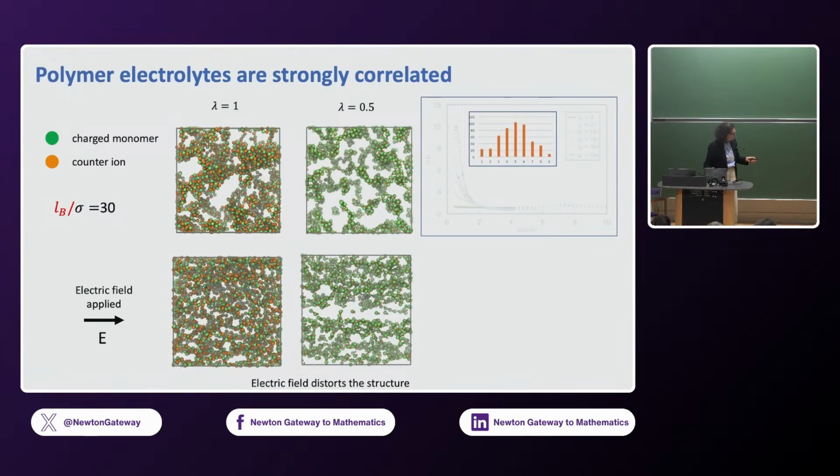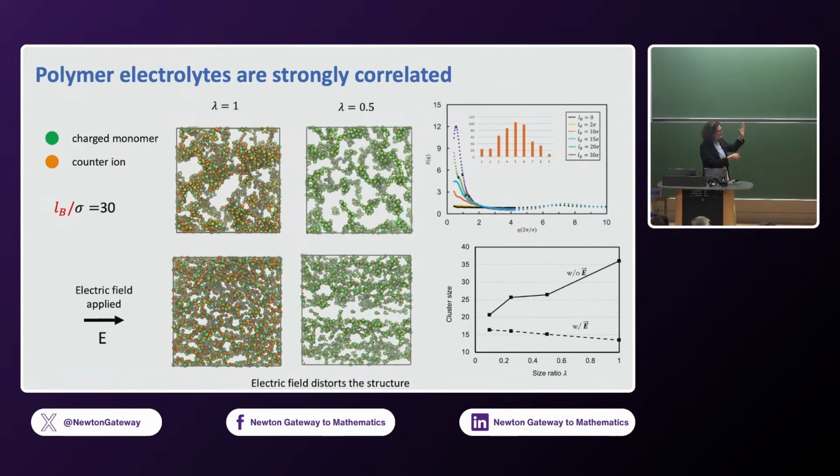And because we talk about multi-component systems, I like to also show this example. In these systems, the charges are random when you make them, so they are really multi-component systems. If you just take two components, if the molecular weight is, say, 50 or 20, you have 10 to the 20 different chains. So even if the mean concentration has some number like 0.5, they have completely different sequences. They are very multi-component systems, and they don't seem to precipitate, but they form these clusters that are percolated. And so they are strongly correlated.